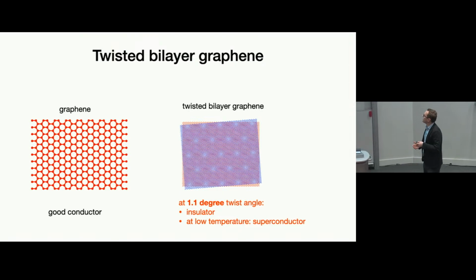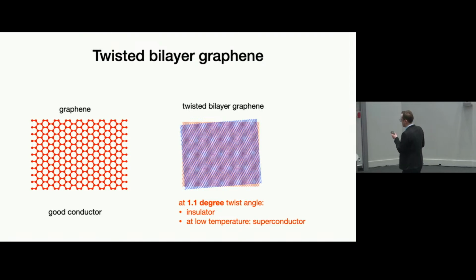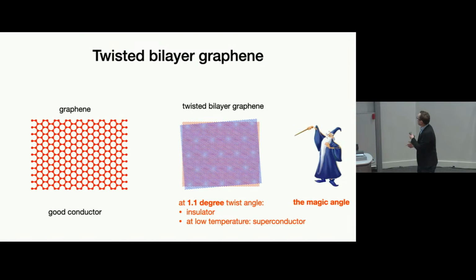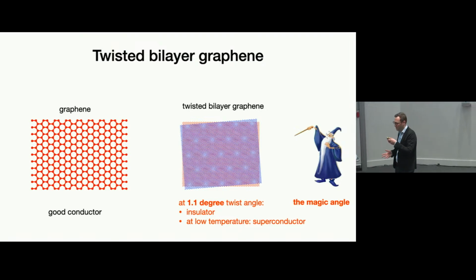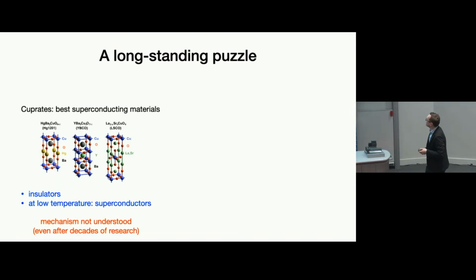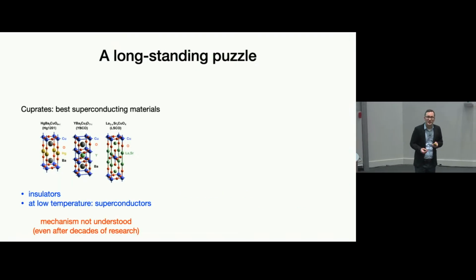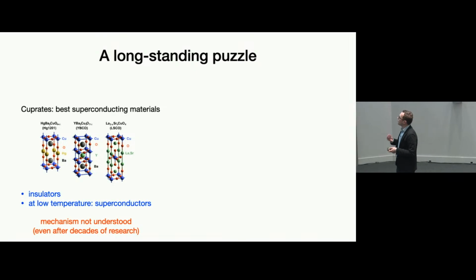And what is even more intriguing is if you cool it down to a low temperature, it turns into a superconductor, a perfect conductor of electricity. This is why, here comes the magic, this rotation angle of 1.1 degrees is called the magic angle, because something very special happens at that particular rotation angle. Now, these phenomena are quite reminiscent of another very intensely studied class of materials, the cuprates, which are currently the best known superconducting materials, and you can see there are some examples of that family of materials.